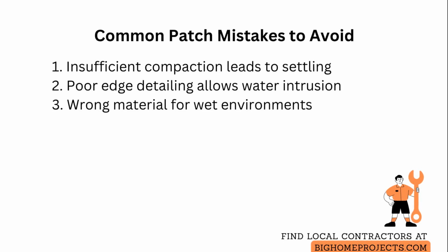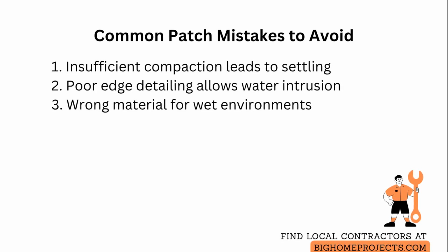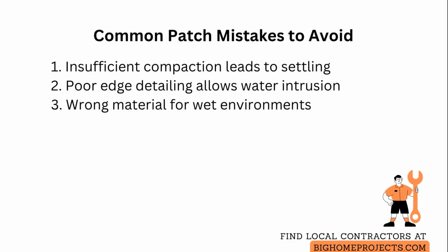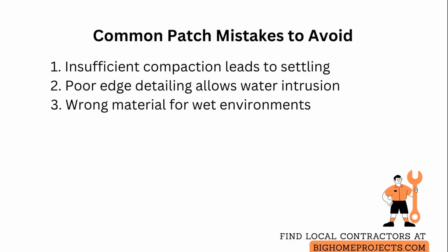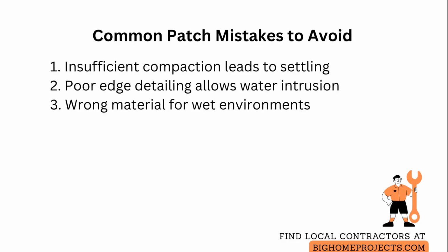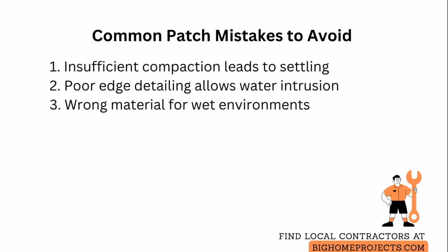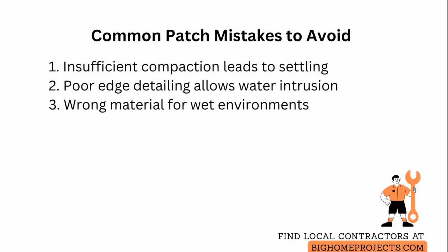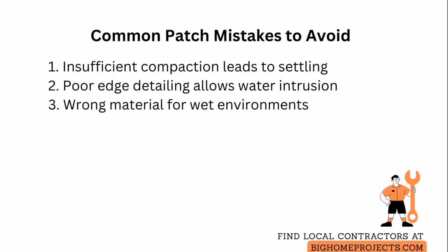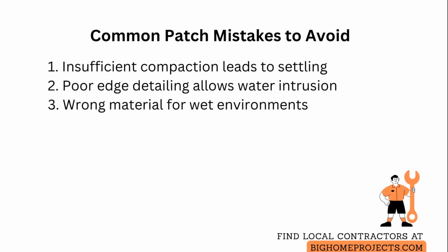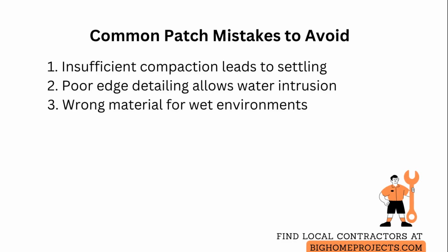If edges are feathered instead of square or sealed, water will track under the patch, so cut back to sound material and create a slightly beveled or keyed edge and apply a perimeter seal. If the patch material is not formulated for moisture exposure, it will deteriorate quickly, so check product technical data for water resistance and select polymer-modified or membrane-forming options for persistent moisture.